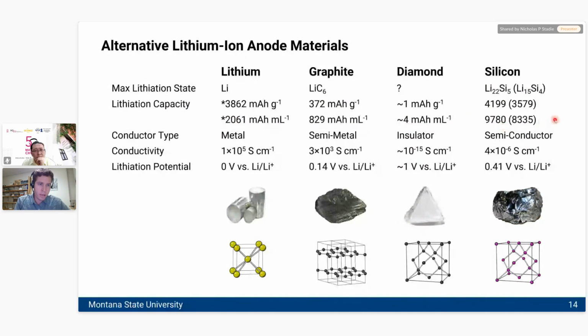This is actually a pretty common property of materials that store very light elements like hydrogen and lithium. I come from a hydrogen storage background, and it's well known that metal hydrides can also densify hydrogen to higher densities than you can get in just pure solid hydrogen. And so the same effect is being shown here. You can take lithium and put it into silicon and get much higher density lithium than you could in just bulk